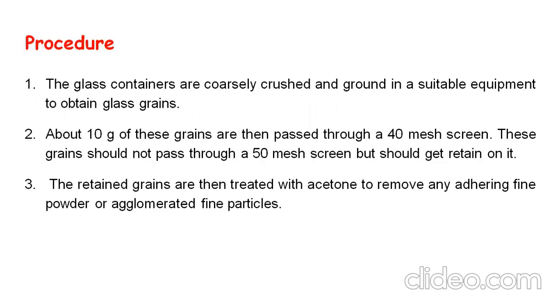Procedure. The glass containers are coarsely crushed and ground in suitable equipment to obtain glass grains. About 10 grams of these grains are then passed through a 40 mesh screen. These grains should not pass through a 50 mesh screen but should get retained on it. The retained grains are then treated with acetone to remove any adhering fine powder or agglomerated fine particles.